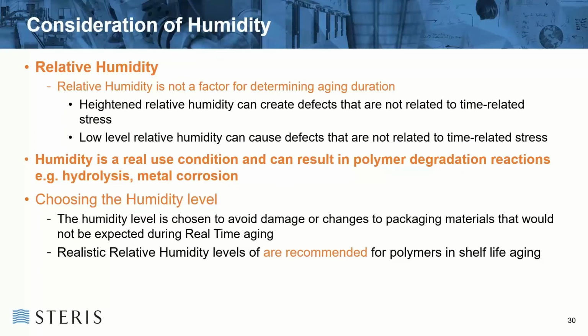And there's no point in doing that, because it's not going to give you anything that is time related, a time related stress, I should say. Typical levels that are chosen should be chosen to avoid any significant damage to the packaging or the product. And typical levels that are being suggested will be between 45 and 55 percent humidity. Again, what you're trying to do is avoid damaging your product unnecessarily.